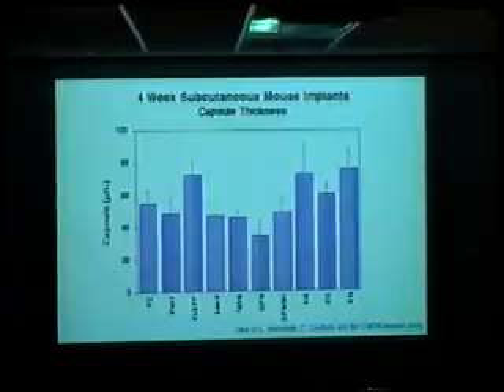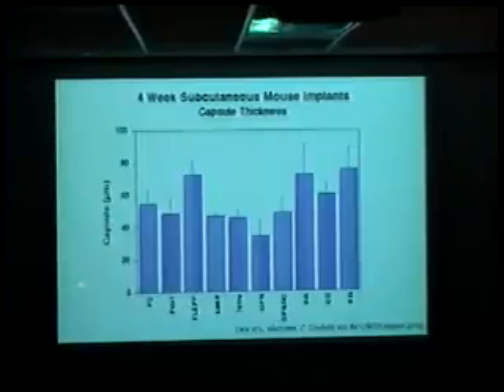In fact, when we implanted them all, certainly within the error, they were all the same. There's one material that can be statistically different from some of the others. This is an osteopontin immobilized material. I'll talk about this one a little bit later. But basically, they all healed. This is the foreign body capsule thickness. They all healed just about the same, in spite of huge differences in the surface properties.